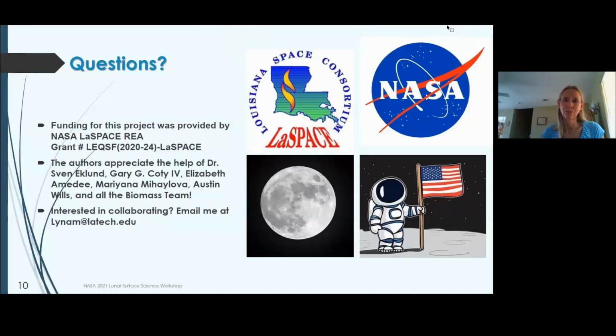So, we are in the process of testing a number of different lunar-based concretes with binders that can be extracted from regolith, things like calcium sulfoaluminate, magnesium oxychloride, and we're curing those in reduced pressure environments to characterize the effects on mechanical properties as the pressure goes down. So, might be interested in talking with you about your planned lower pressure tests.